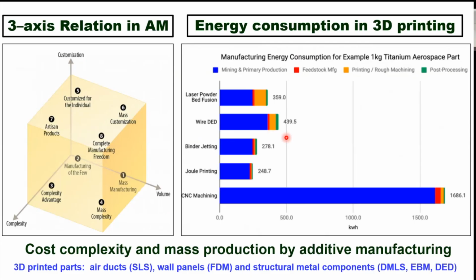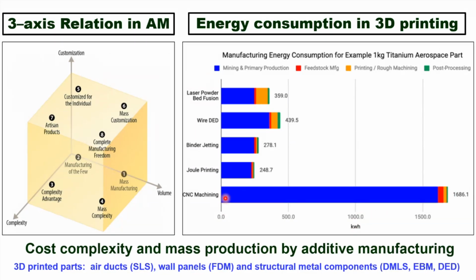What is important, I mean, why we pay so much attention is simply explained by this view graph here. So if you do machining alone, then the energy that you consume for a particular component, so typical conventional machining, would require a much larger energy. Compared to that, when you have a wire-fed direct energy deposition or laser powder bed fusion and so on, this is almost like 1/5 or maybe an order of magnitude lower. Which says that this is a very energy economy process.